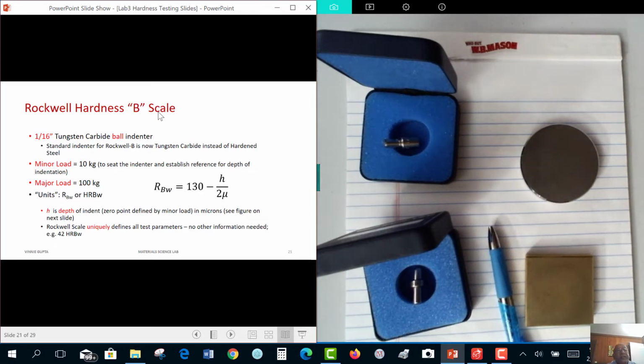So if we look at Rockwell hardness B scale, this 1/16 inch tungsten carbide ball is the standard indenter now, tungsten carbide instead of hardened steel. So often when you see this W at the end, it means that it is following the new standard, tungsten carbide. If it was the old standard hardened steel, you would not see this W after that. So what we do is we apply a minor load first. I'm going to show you a video in a few minutes. In case of B and C scales, the minor load is 10 kg. It is used to seat the indenter and establish the reference for depth of indentation measurement. And then the major load we apply is 100 kg.